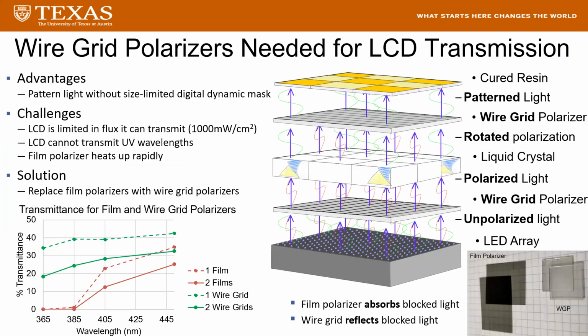So our solution is using a UV backlit LCD monitor with the film polarizers replaced with wire grid polarizers. You can see a schematic on the right of how an LCD functions, with two orthogonally oriented polarizers that each only transmit one polarization of light, sandwiching a layer of liquid crystal. Any pixel of the liquid crystal that's energized will rotate the polarization of light, allowing that light to transmit through the second polarizer. There are multiple SLA printers on the market that use LCD screens to pattern UV or near UV light. However, these printers are highly limited in the types of resins they're able to print with due to the low transmittance through LCD screens, even monochrome LCD screens.